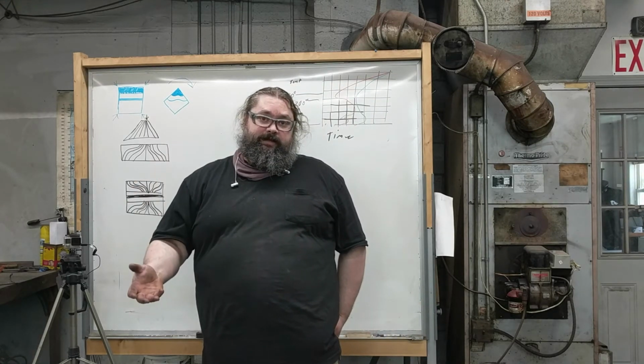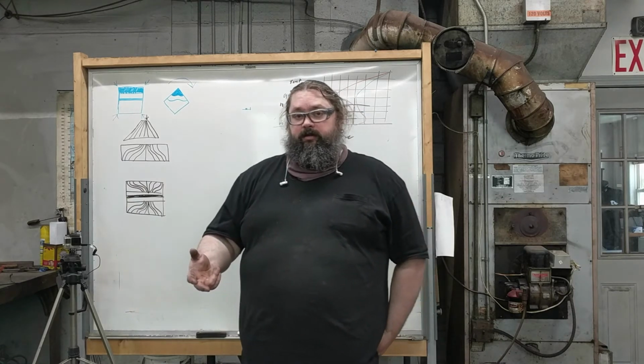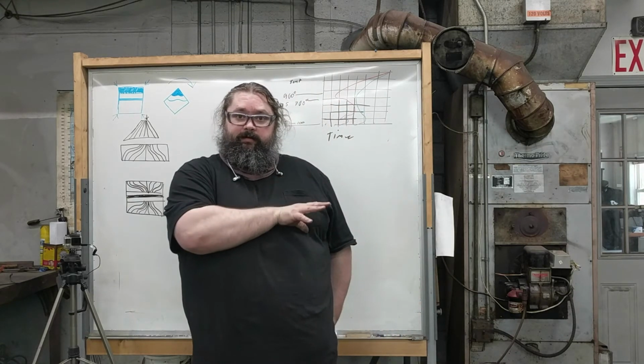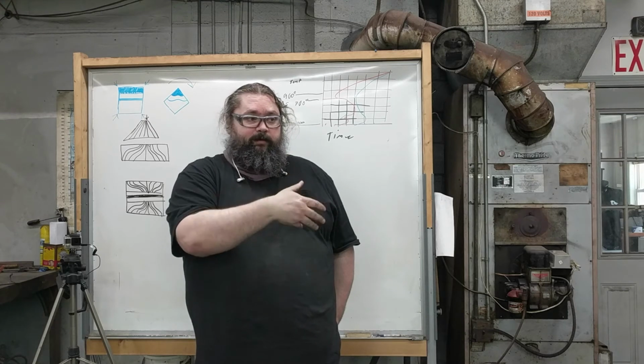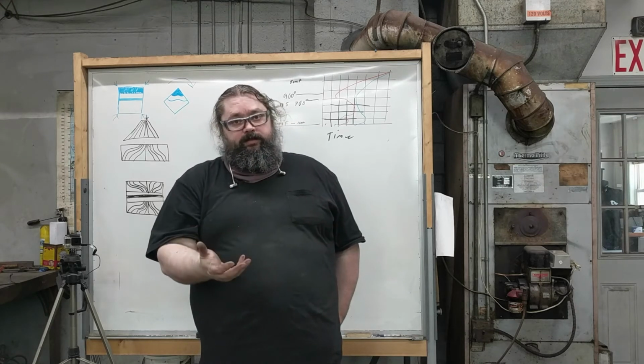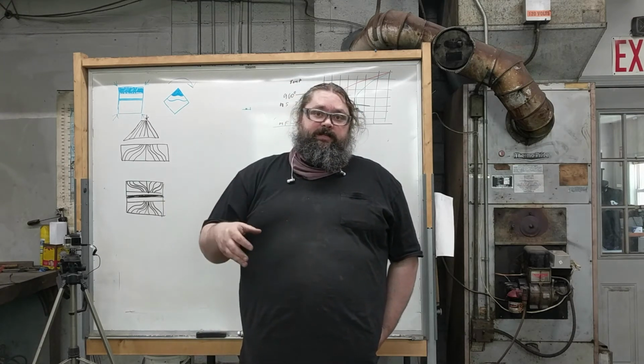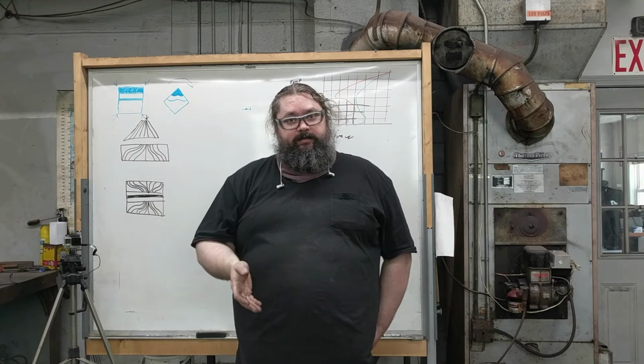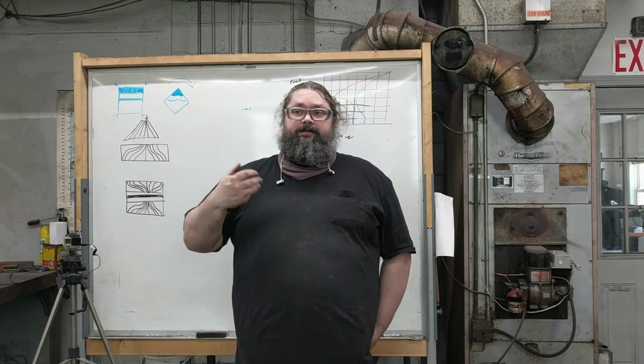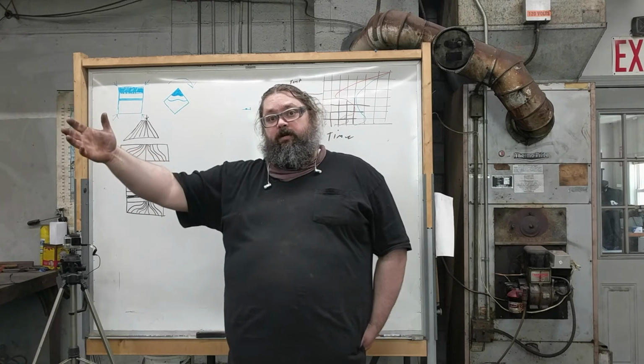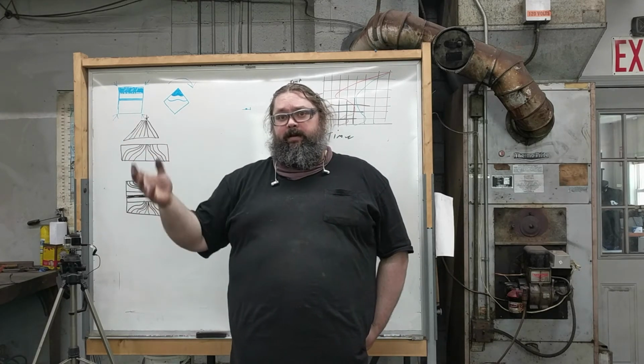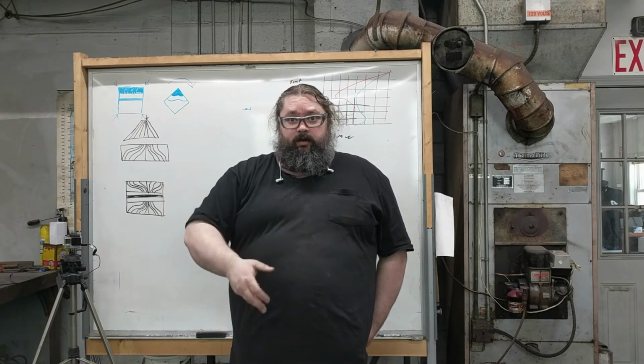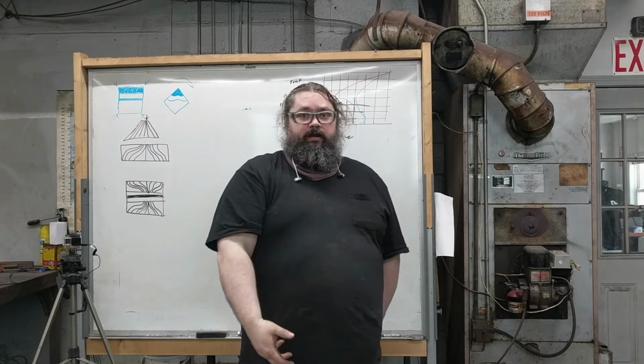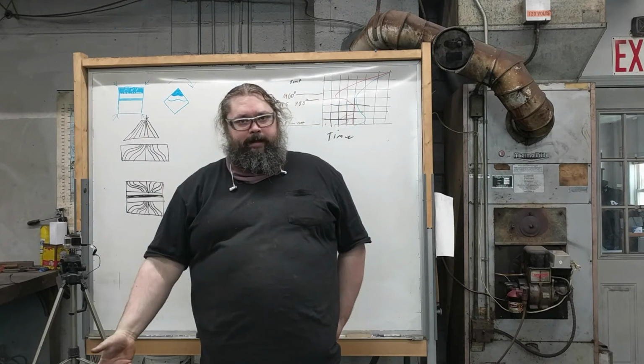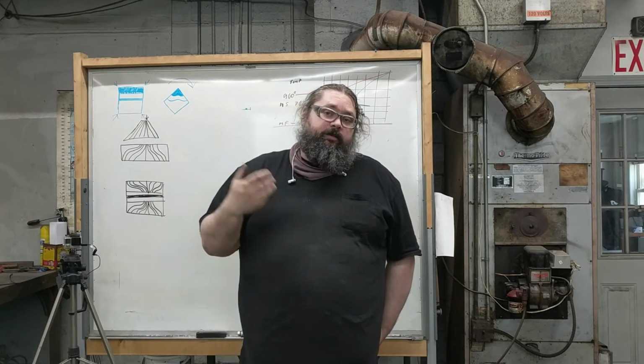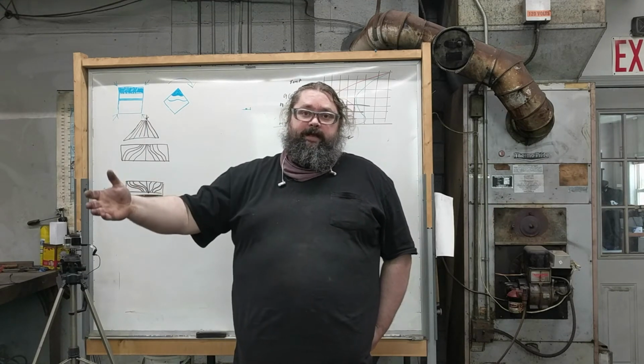then you end up with much less retained austenite. The next thing, you want to snap temper so you have a little bit of temper in the steel. That'll convert some, but it also takes some of that stress away. And when you put it in the dry ice slurry or the nitrogen, it's under a great deal of stress from that austenite all converting. It's as if it's hardening in a minute. So that hour soak in there, you want to be tempered when you go in, otherwise you risk a lot more cracking. But after that, you're pretty much all converted to martensite.